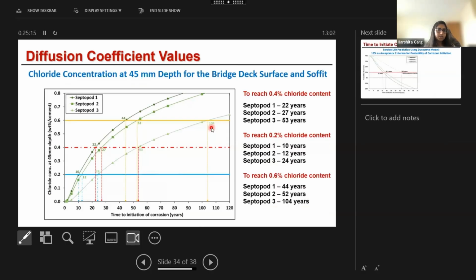Now, chloride concentration at 45 mm depth for the bridge deck surface and soffit can be seen here at 3 different points: 0.2 as the minimum chloride content, 0.4 as the average chloride content, and 0.6 as the highest chloride content it can reach. Considering 0.4 chloride content to reach that point, it would take around 22 to 27 years for septopod 1 and 2 near the deck surface, and around 53 years near the soffit area.